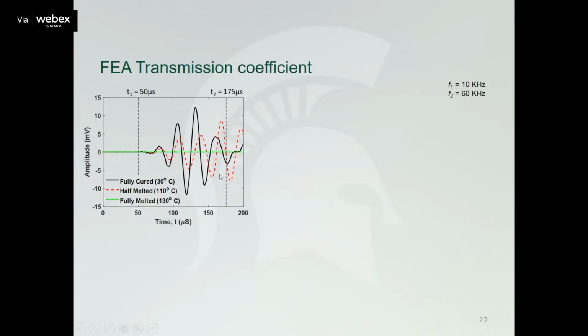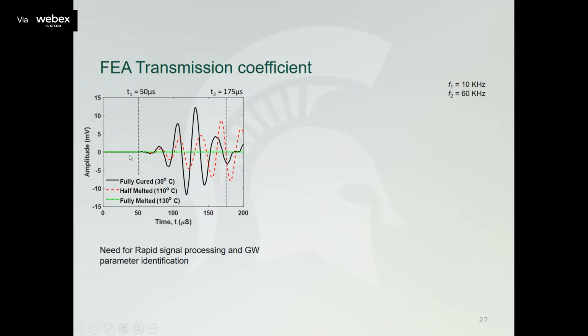So you can get the signal amplitude versus the time. Well, this is the simulated PZT response. Remember, you have two PZT applied on each substrate end, and we can measure that. So you can see for fully melted, then this amplitude is 0, right? So no energy has been transmitted. Well, for half melted versus fully cured, then you can clearly see for the fully cured, you'll see the energy or the signal has been captured.